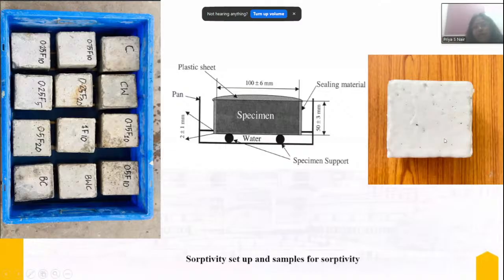So this is the sorptivity. We can see that the initial and final sorptivity were determined. The initial sorptivity was taken up to 6 hours, and after that, up to 6 days, the secondary sorptivity was taken. In the case of the higher and lower consortium samples, very tremendous changes were seen. The higher consortium has lower secondary sorptivity than the lower one. This is the experimental way. This is the sample for the sorptivity testing. Four sides of the cube we block, plugged with wax or something, and the 2 sides we leave open. It is placed in the water. This figure gives the maximum hint on how we can do the sorptivity test.